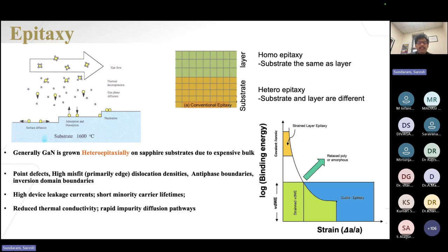That's the availability nowadays. Because we are growing it heteroepitaxially, we will be generating a lot of point defects. Misfit dislocations, antiphase boundaries, and inversion domain boundaries are there inherently. This leads to high device leakage currents and short minority carrier lifetimes. It also reduces the thermal conductivity, and acts as impurity diffusion pathways. So the leakage current of the device will be higher, and this leads to stochastic failures of devices.